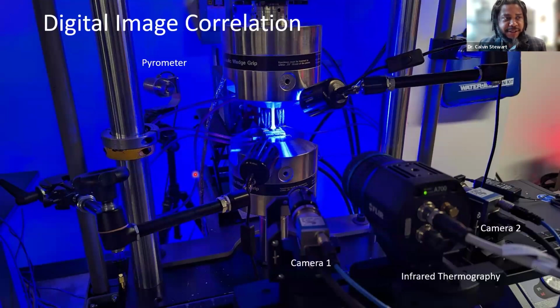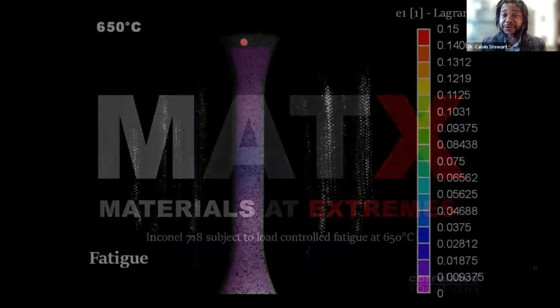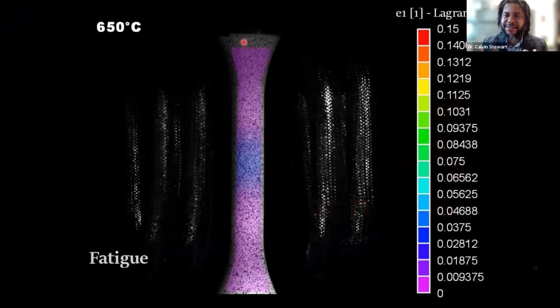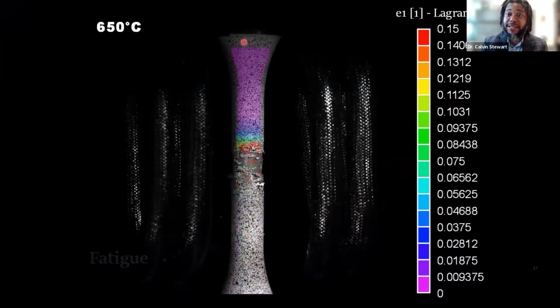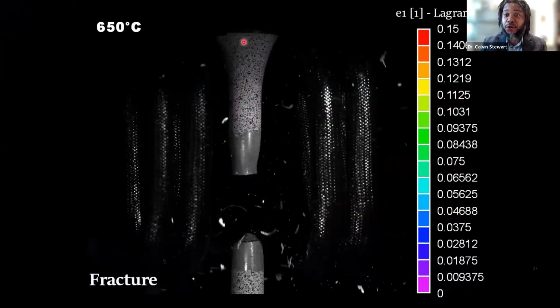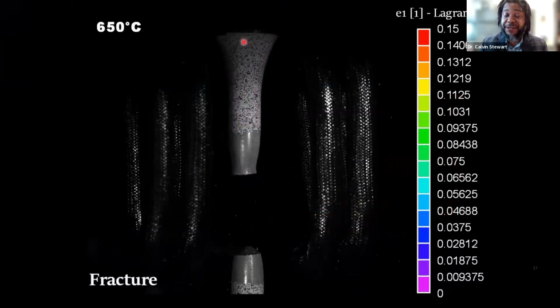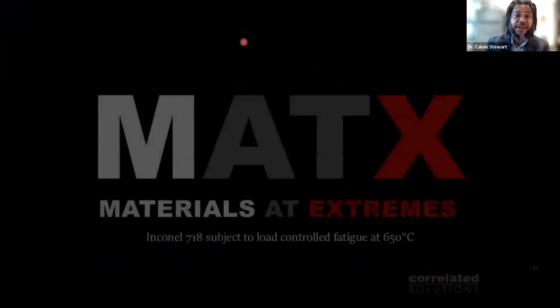So to do that, we're using this technology called digital image correlation. And we're doing a special version of it. We're using infrared cameras, so infrared. We're using 2 white light cameras, so it's 3D, and then it's digital image correlation. This technology allows us to track a speckle pattern that exists on the surface of our samples that we apply to it, and to be able to back out the displacements, as well as the calculated strains from those displacements in 3D on the surface of these samples.